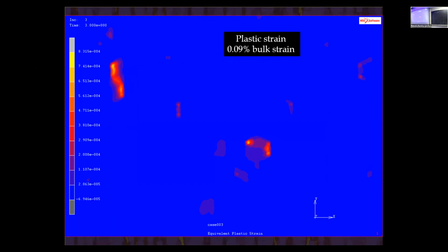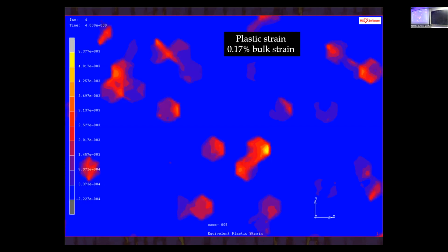So here is when we first get to see some yielding. So here's a grain. You can clearly now see the hexagonal shape of this grain. And there's a little hexagon here that's yielded. Some grains that are weak happen to be somewhere in the force arrangement that they hit their yield strength, so they began to yield. And the next little bit, now you can really see the hexagonal shape grains, unlike in the stress distribution.